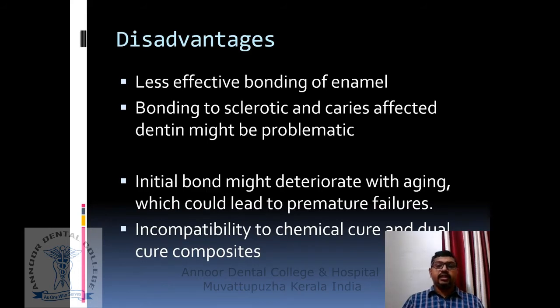Why this bond deteriorates with aging is because your dentin bonding agent is going to bond with the collagen meshwork that is organic. It has lost its mineral protection. It will degenerate over time. So your bonding also will disintegrate or deteriorate with time. Then there are a few difficulties, like incompatibility with chemical cure and dual cure composites. So these are the disadvantages. The major one is less effective etching of, or bonding to, enamel. The second one is that bond strength will deteriorate with aging.